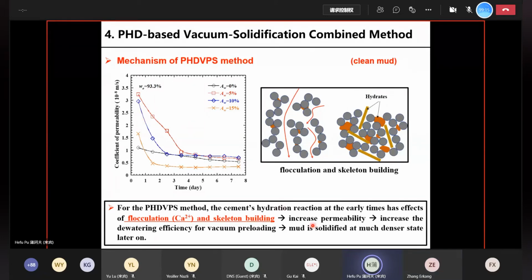The increase of permeability is attributed to the fact that the cement hydration reaction at early times has an effect of flocculation due to the generation of calcium ions, and also the hydrates have some skeleton building effect. It pulls the particles together and increases the pore size, and because of that, at the very beginning, the dewatering efficiency can be improved for vacuum preloading. And because of that, the mud is solidified at a much denser state later on.